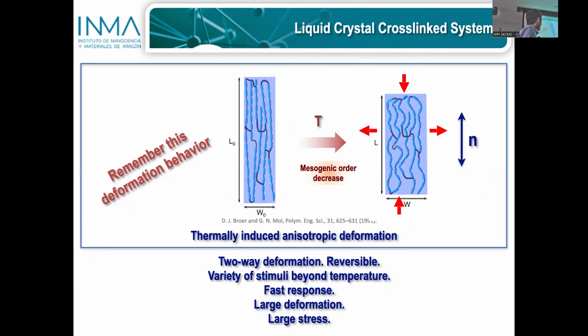Essentially what we have is this polymeric network, a liquid crystalline polymeric network, a cross-linked system that, depending on the degree of cross-linking, we call network or elastomer. Elastomer is a low degree of cross-linking. A network is a high degree of cross-linking, and this has an impact on the mechanical properties, but also on the degree of deformation that we are able to achieve.